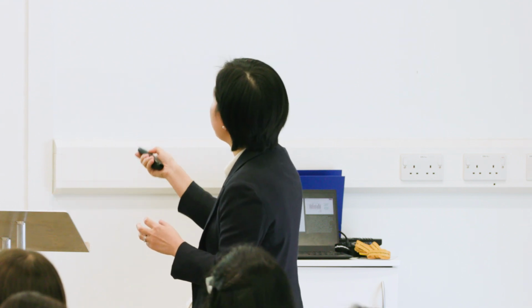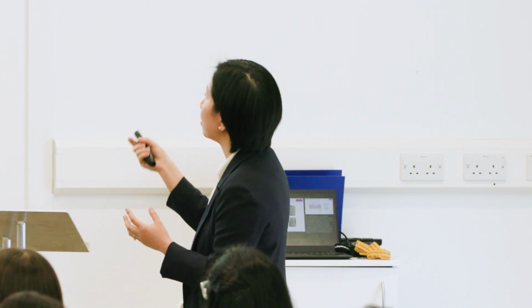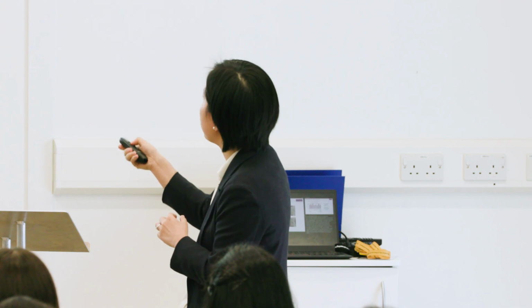And in some of the cases, those strengths obtained from graphene green concrete are even less scattered. So those consistent results can lead to higher characteristic strengths for structure design purpose. And when we look at the pictures of the testing specimen, we can see that there's perfect bonding basically between the cement paste and the aggregates. There's almost no difference at the interfacial transition zone between these two mixtures.